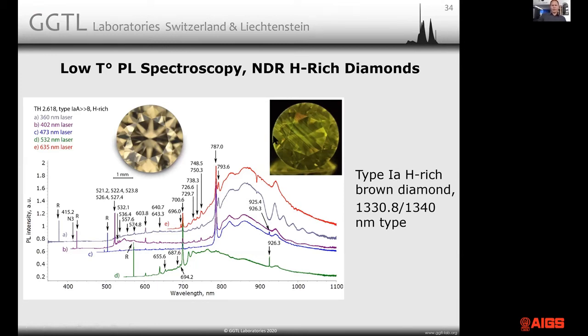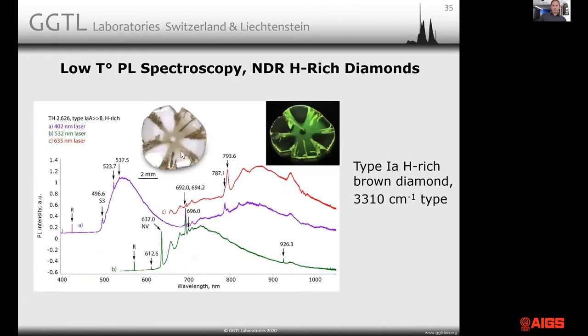Here, the same thing of the cuboid octahedral stone. The green fluorescence that's so spectacular in these stones is always confined to the brown sectors or to the arms themselves. This green fluorescence originates from the S3 center. You can see it in trace A. This broad band centered at about 540 nanometers translates directly into green fluorescence. The S3 center is nickel related. So again, you can see nickel is quite important in brown diamonds that are hydrogen rich.